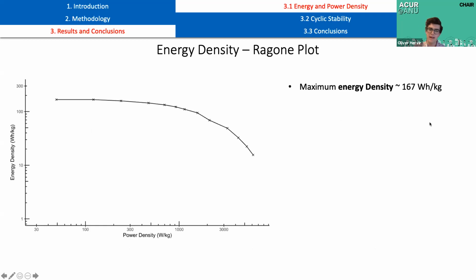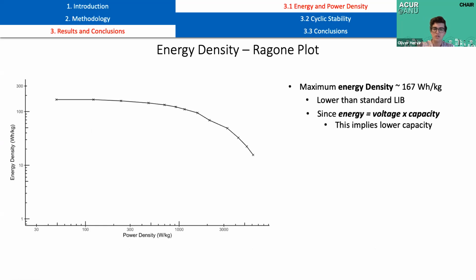The first is that the maximum energy density of our battery is 167 watt-hours per kilogram. And this was unexpectedly lower than a standard lithium-ion battery. And so we set out to rationalize this. And we thought, well, if energy is simply voltage multiplied by capacity, and we know from before that the voltage of a dual-ion battery is bigger due to its chemistry, then this must mean that the capacity of our dual-ion battery is actually smaller. And this can be rationalized by thinking about the anion PF6, which is really quite large and therefore might not be able to fit into the electrode very well.